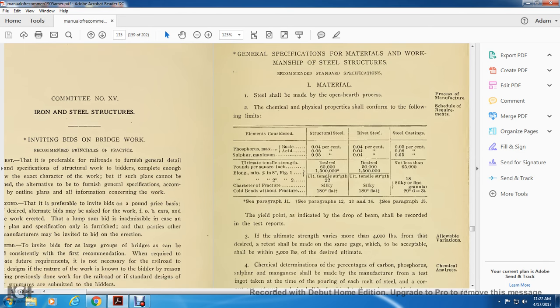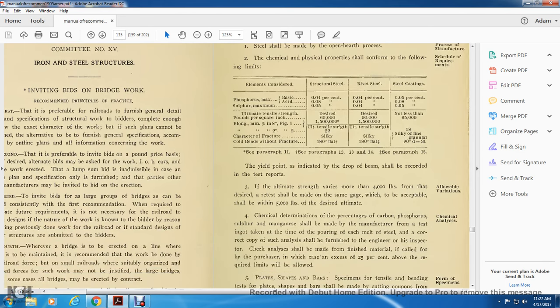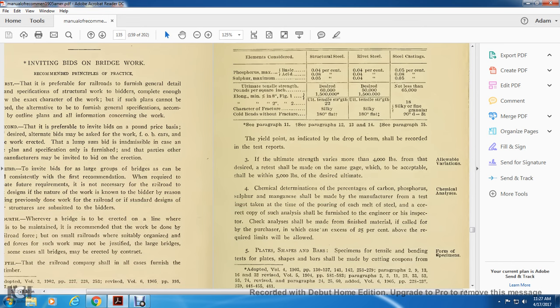The yield point is indicated by the drop of the beam, and it shall be recorded with the test reports. If the ultimate strength varies by more than 4,000 pounds from the desired result, a retest shall be made with the same gauge, with which the acceptable variation shall be 5,000 pounds from the desired ultimate.